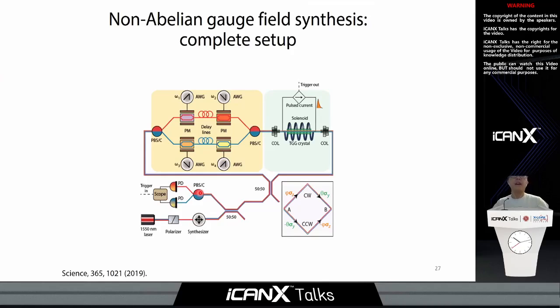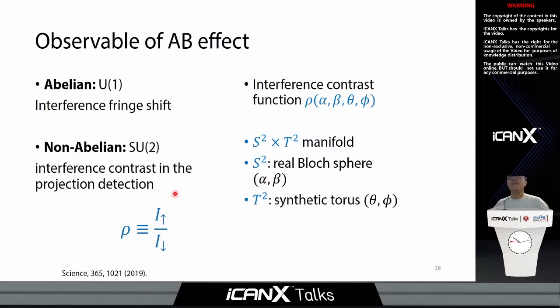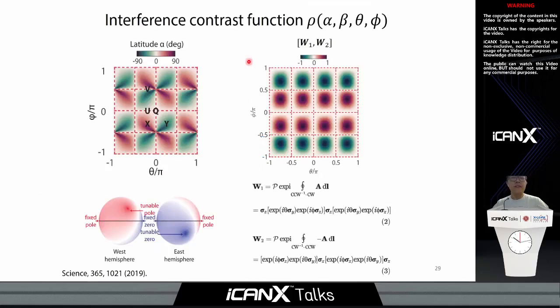So the observable of our AB effect is defined as the contrast between the up pseudospin and the down pseudospin that's defined on this S2T2 manifold, which has 4 parameters that we can tune. And we can show this interference contrast function rho corresponds to this interference contrast on the Bloch sphere that's highlighted by a set of tunable poles and zeros. And we're interested in the tunable poles and zeros as a function of the non-Abelian gauge fields theta and phi.